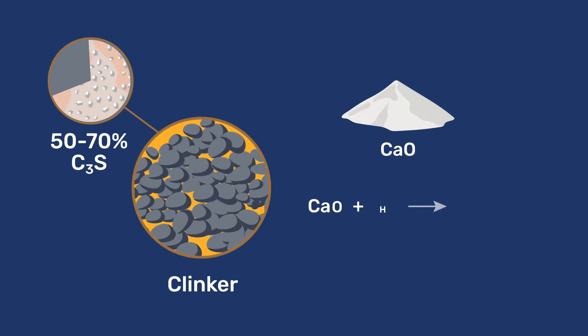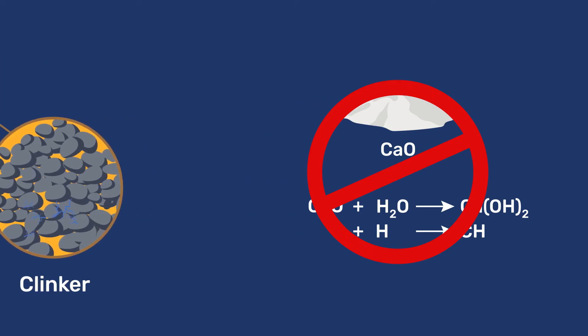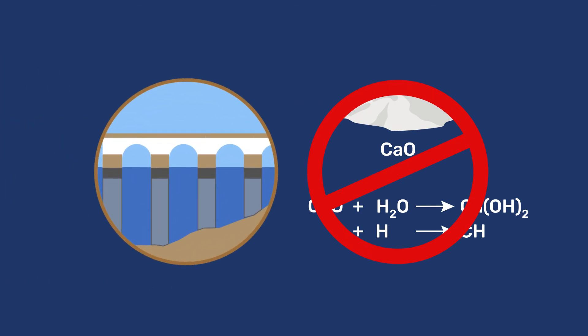Apart from this, excess free lime, or calcium oxide, should be avoided. Indeed, its reaction with water forms calcium hydroxide, which, when formed from free lime, can cause expansion and cracking of hardened cementitious materials. So, to ensure their dimensional stability, the amount of free lime must be minimized, keeping it below 1-2% of the clinker mass.